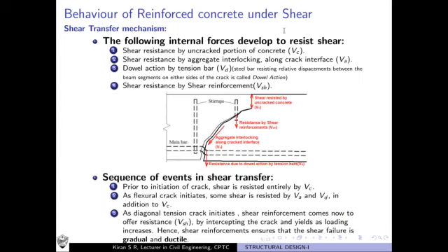Now, since we are interested only in the mechanism by which shear gets transferred in a beam, because in this class we are going to study how to design a beam for shear, we are going to study the shear transfer mechanism. So what are the different ways by which shear stress is resisted by our reinforced concrete member? You see this figure. Initially, the concrete undergoes a crack at the extreme tension fiber, which is what we call the flexural crack. But as you keep increasing the load, the crack moves closer to the neutral axis. It inclines and becomes 45 degrees. Okay, and it is now a shear crack. So overall it is a flexure shear crack which we obtained.